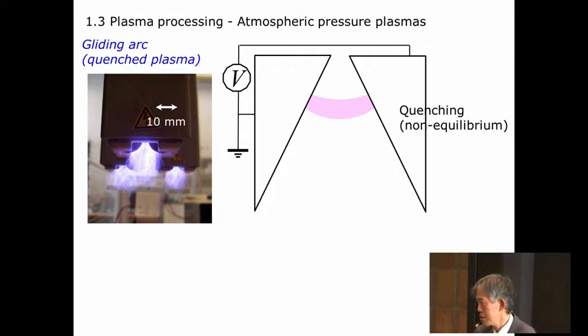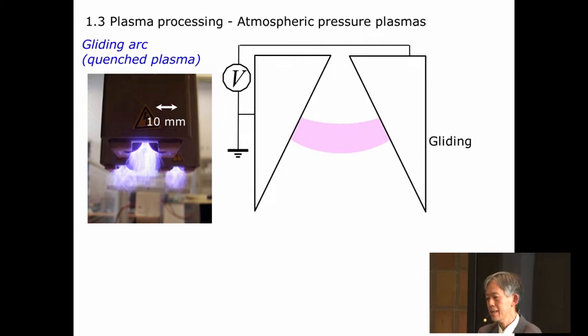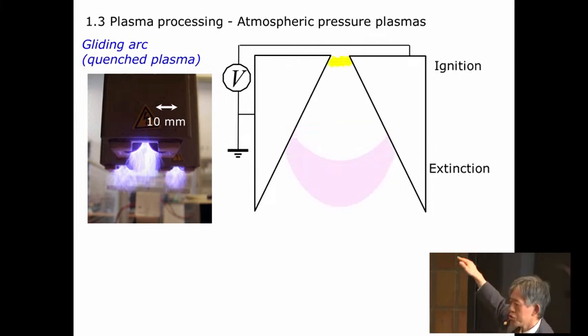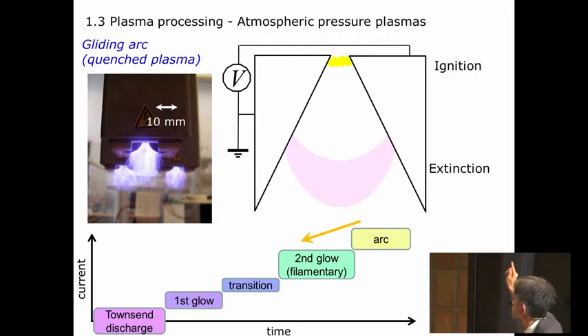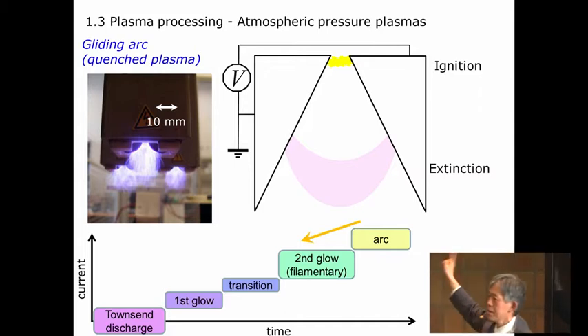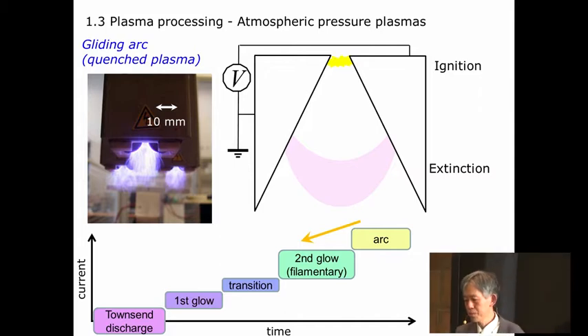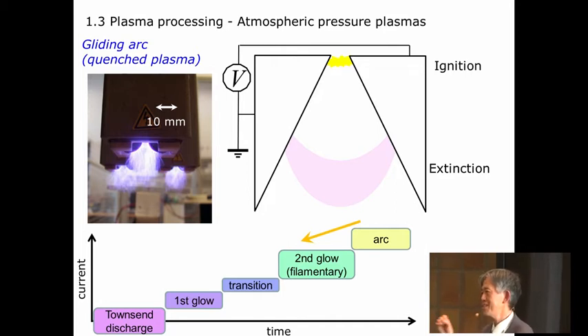That can be used for normal polymer processing. Then extended gliding. Then at some point, re-ignition, and then the non-equilibrium plasma is extinguished. That is the life of the gliding arc. In this sense, gliding arc is not an arc, but quenched plasma coming from the arc, but cooled down to the non-equilibrium condition. It is potentially quite interesting because initially it is an arc, then the impedance of the plasma is quite low. Therefore, it's very easy to introduce very high power without any serious problems compared to normal low temperature plasmas.